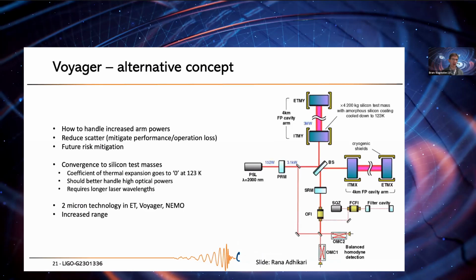However, there are some alternative concepts that are also of interest. One of those concepts is the Voyager interferometer. And that can utilize the same infrastructure as the LIGO, the Virgo, or the KAGRA machines. However, they operate at, say, 123 Kelvin and use silicon test masses, and predominantly the reason is that silicon has a thermal expansion that goes to 0, so the heat dissipates straight out of the test mass. So we don't have thermal deformations as much as we currently have.